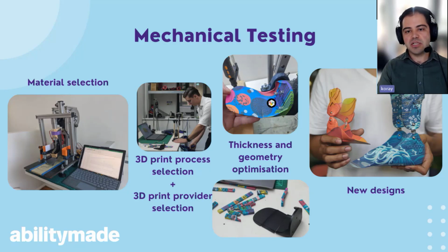I'll go into a bit more detail about the results of the testing that we've done. Essentially, we've had parts printed at close to 50 locations using a variety of print processes: HP MJF, SLS, SAF. We've been doing a lot of testing around it, and I'll show you the results of that testing in a moment. We have found that the HP Multi Jet Fusion 580 printer with its color, the PA12, essentially, when you couple it with the vapor polishing, produces really amazing outcomes.